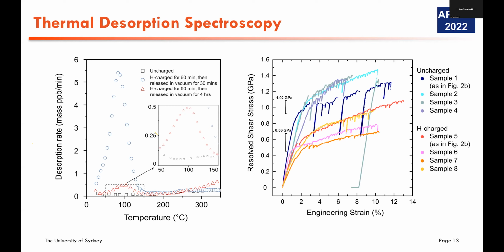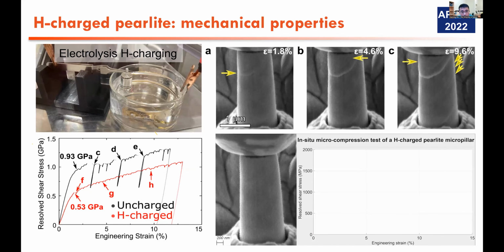Maybe you show the 0.5 atomic percent in ferrite observed by atom probe. So it means the ferrite still has a lot of ability of trapping so much hydrogen. But your TDS analysis shows a very small hydrogen trapping. Sorry, this TDS is conducted with this bulk sample, the in situ charging sample.